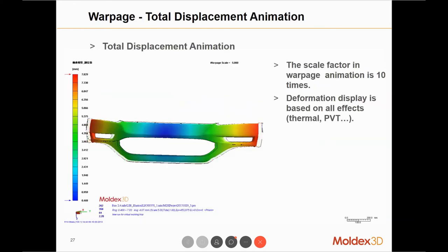Okay, and after ejection, the most important thing is the deformation. So Moldex3D warpage calculation considers not just the thermal properties and the PVT of the material, but also the mechanical properties altogether, and calculates the deformation of the part. And like I mentioned before, for thermoset, normally the volumetric shrinkage is smaller compared to thermoplastic. So sometimes it is difficult to tell whether the part is shrinking evenly or actually there is any bending or even twisting.